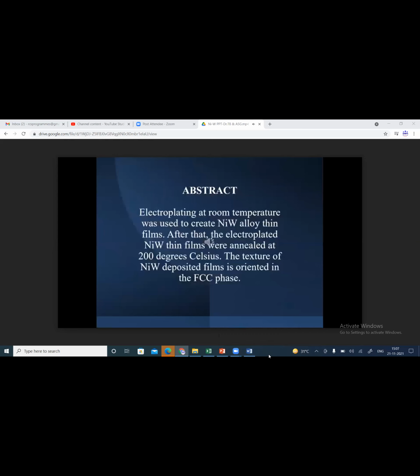Abstract. Electroplating at room temperature was used to create nickel-tungsten alloy thin films. After that, the electroplated nickel-tungsten thin films were annealed at 200 degrees Celsius. The texture of nickel-tungsten deposited films is oriented in the FCC phase. Morphological, structural, and mechanical characterizations were performed on them. On the surface, nickel-tungsten films were brilliant and uniformly covered. Nickel-tungsten film deposits were also nanoscale, with an average crystalline size of roughly 92 nanometers. After annealing, the microhardness of nickel-tungsten was 138 VHN.